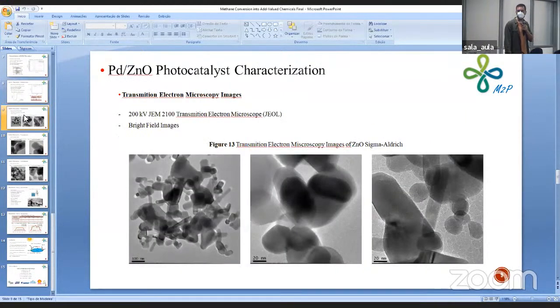Here we have some transmission electron microscopy images. First, figure 13, images of the pure zinc oxide. And we can see that there is no uniform morphology around the particles. We have some spherical particles in here, some rod particles, but no uniformity. In their sizes too, we have particles in the range of 20 to 300 nanometers. So this is not a homogeneous sample.